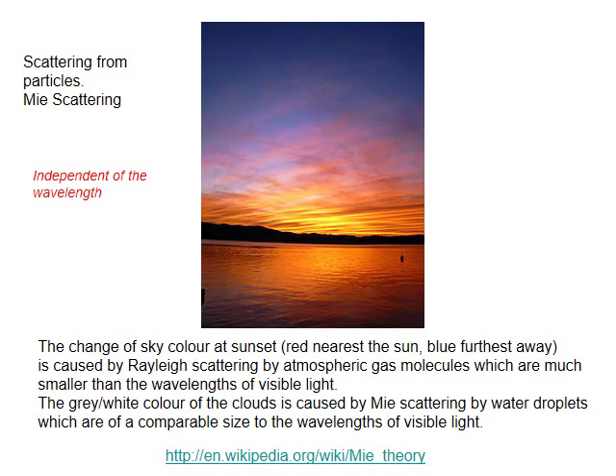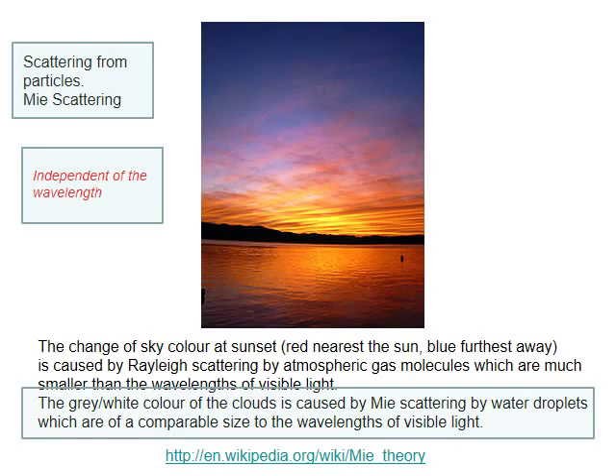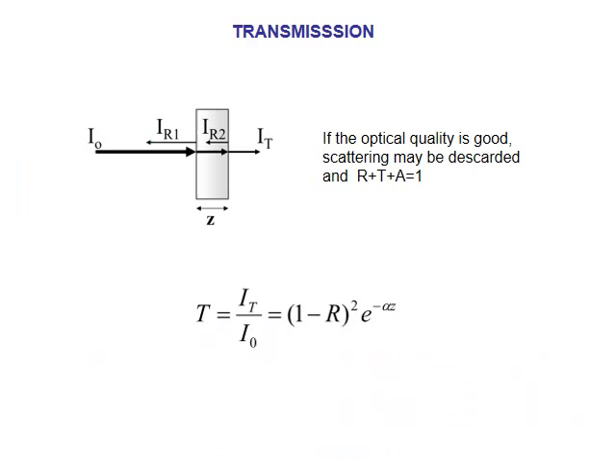Scattering from particles is independent of the wavelengths. It's given by the Mie scattering. So the change of sky color at sunset, red nearest the sun and blue furthest away, is caused by Rayleigh scattering by atmospheric gas molecules, which are much smaller than the wavelength of visible light. The gray-white color of the clouds is caused by Mie scattering, by water droplets which are of comparable size to the wavelength of visible light. Transmission, therefore, is defined by the reflection and absorption. If the optical quality is good, the scattering may be discarded, and so the transmission will be given by this expression.